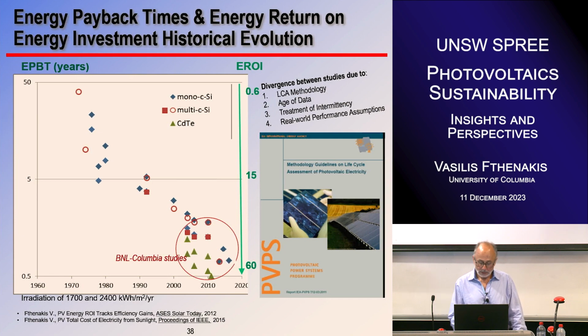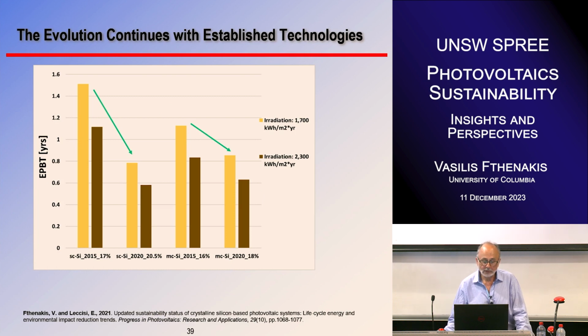Now, the evolution continues with established technologies. You can see here, over the 5 years from 2015 to 2020, a big reduction in the energy payback times of crystalline silicon. Why? For the most part, it is the reduction of thickness and of kerf loss, because the industry transitioned to diamond wire cutting from multi-wire slurry cutting. Instead of 145 micron loss with every cut, we are now at 65 micron loss. Thinner wafers, 170 here versus 200, and also higher efficiency, 17% to 20.5%. About 25% better in multicrystalline, but the most impressive is with the cast-mono and the Czochralski silicon, which is a very high-demand type of silicon.